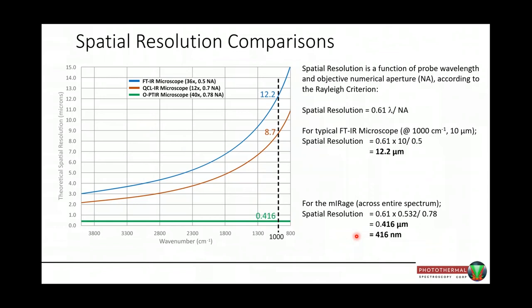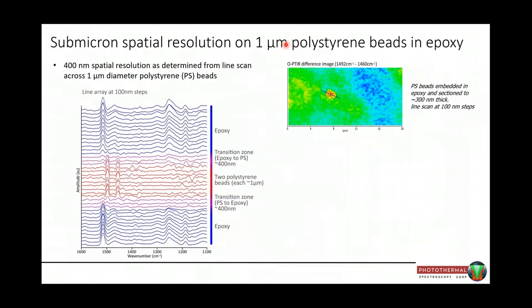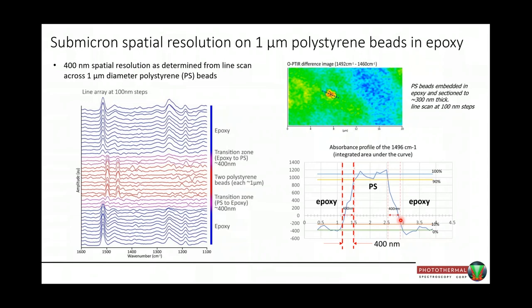Here's an example of a sample, 1 micron diameter polystyrene beads embedded in epoxy side by side. We collect a series of spectra along a line across the boundary, going from the epoxy into the polystyrene and back into the epoxy, and these spectra transition within about 400 nanometers from being epoxy-like spectra to polystyrene spectra.